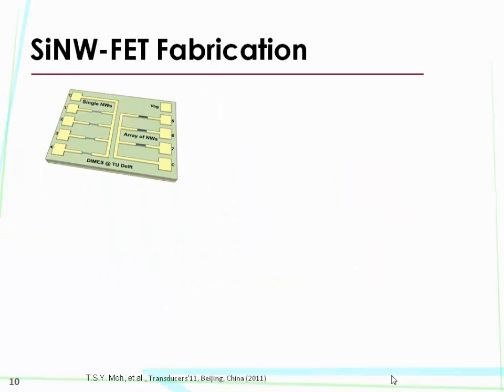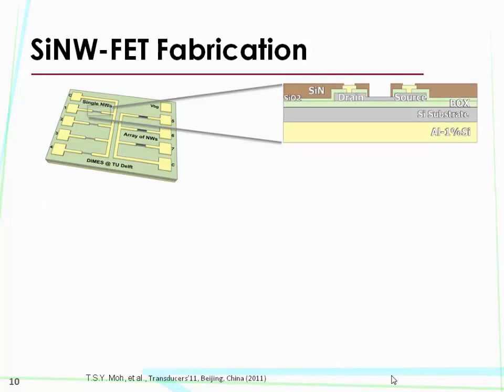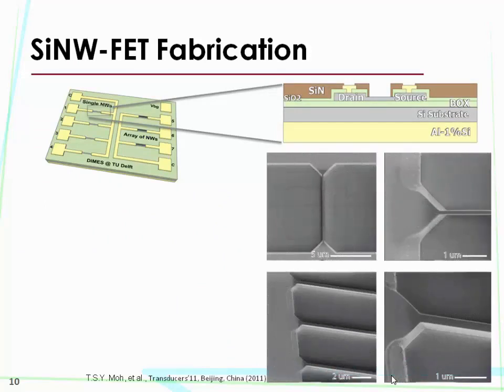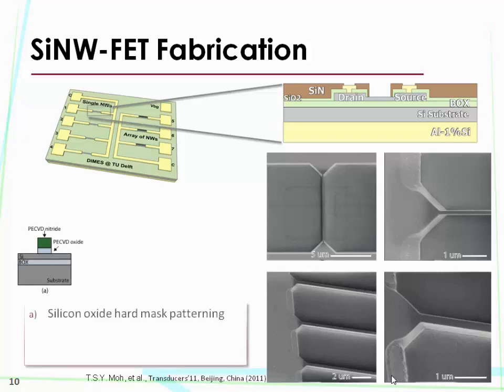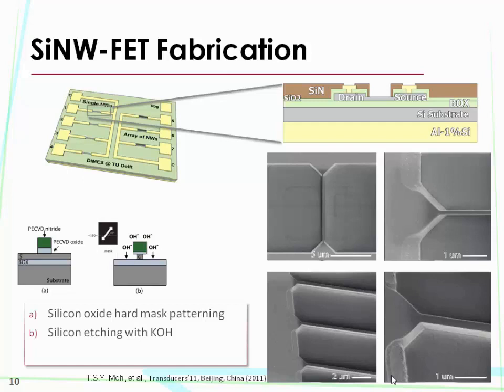The fabrication was performed at TU Delft — the Delft University of Technology. Here we can see a cross-section of the device we used. The fabrication process is a pretty simple process that enabled the fabrication of very controllable nanowires in size with very flat and smooth surfaces. We used silicon oxide as a hard mask for photolithography and then used anisotropic KOH etching in order to achieve lateral underetch beneath the hard mask and reach very flat sidewalls. The high-quality structures we obtained helped a lot with the biofunctionalization process, especially in terms of homogeneity.